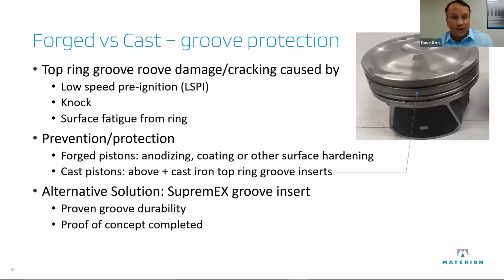And groove damage can come from low speed pre-ignition, and that's why most of the OEM cars have that groove insert in there, depending on whether you tune yours or not. You can have knocking there. You can also have surface fatigue from the ring sliding back and forth if you get some friction there, right? So what can you do on a forged piston? Everybody knows anodizing is a pain in the neck. Trying to get a narrow, deep groove like that anodized is really tough. Putting a coating down there isn't easy either.